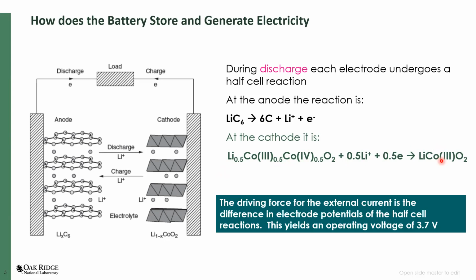In this case of a lithium-ion battery with a lithium cobalt oxide cathode and a graphitic anode, in an organic electrolyte, you get an operating voltage of around 3.7 volts, which can then be put together in these packs to increase the voltage and to deliver a huge amount of current as required. So that is how a battery stores and generates electricity.